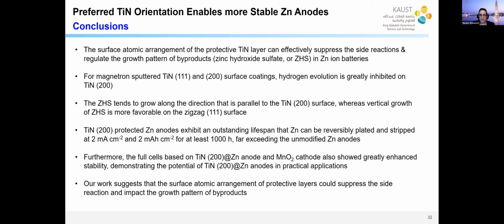So by using this titanium nitride with the 200 surface orientation, which has the flat atoms, we basically lower the barrier for the nucleation of this phase on top of the titanium nitride. And that's why we produce such a good battery.